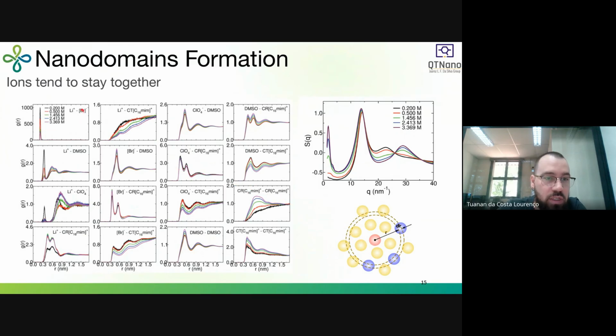And if you look at the interaction between lithium and the bromide anion, we see this very high peak here that says that we have a very strong interaction between lithium and the bromide anion, which was expected because of positive and negative charges. And when we increase the concentration, we see a decrease here in the first peak, but it is still way higher than the DMSO. That means that when we have more ionic liquid in the system, lithium is mainly solvated by the anions, and the DMSO is occupying the second solvation shell.